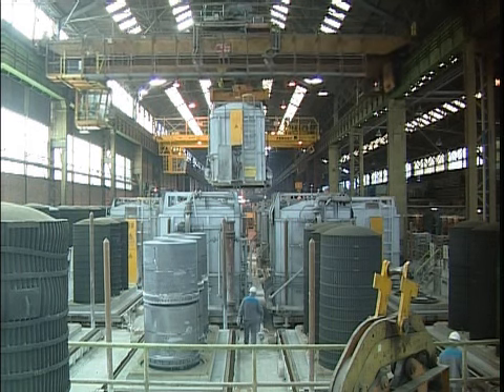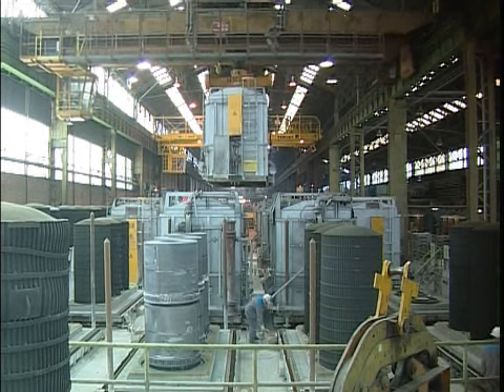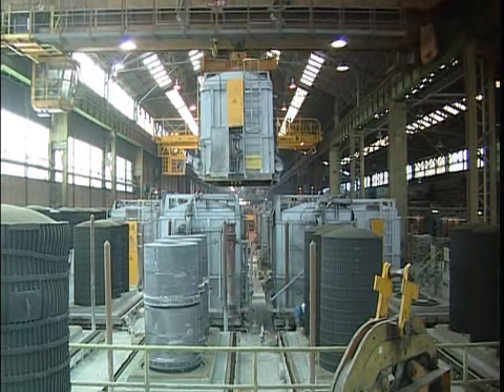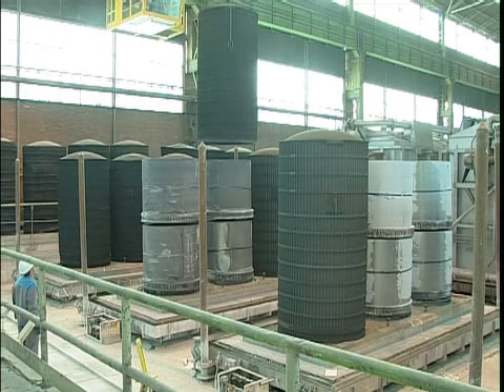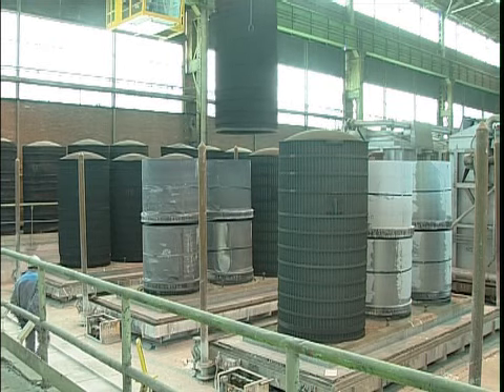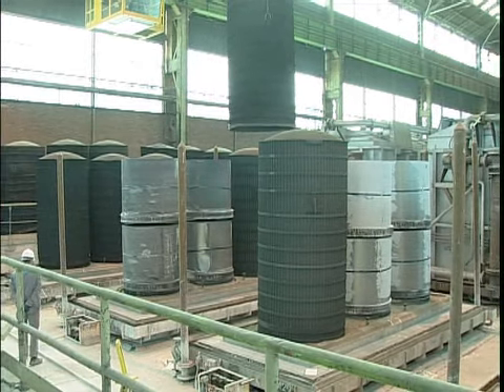In the selection process, there is only one iron crystal in 30 million having the right cube-on-edge orientation, which absorbs all other surrounding crystals. The magnetically preferred direction of the cubic iron crystal is the direction of its cube edges, which by the sophisticated process is aligned into rolling direction. At this production point we obtain grain-oriented electrical steel. With its unique characteristics, the core loss of this textured material is only 1/3, compared with the best non-grain-oriented grades.